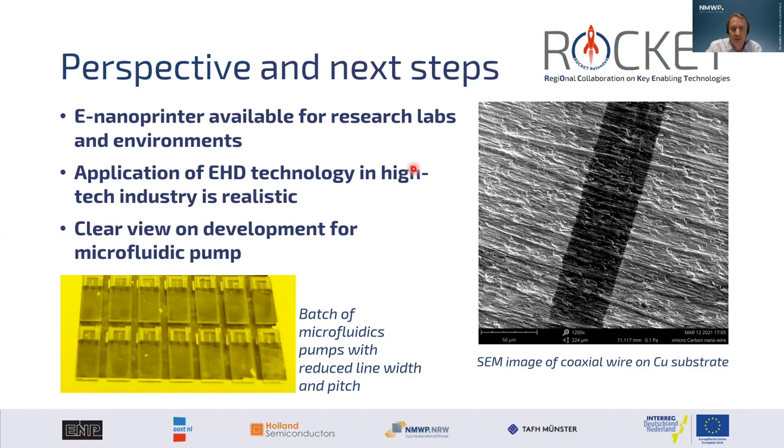Can you say something about the benefits of the electrospinning technology over conventional printing technologies with conductive inks, for example circuit boards? Yeah, sure. Good question. The current printing technologies are typically related to spitting or drop-on-demand systems, like print heads. For inkjet printing, or even other printing technologies, it's very hard to go below 30 micron resolution or feature sizes. That's almost not possible. So the inkjet printing process is limited in terms of accuracy and feature sizes.